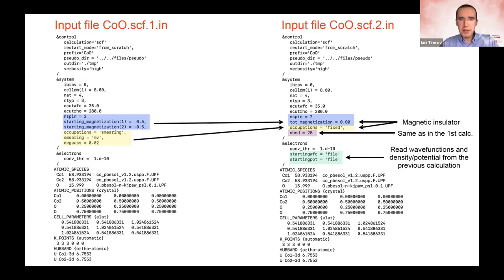In the first calculation, which was the DFT calculation, that was the metallic ground state. You remember we computed in exercise 1 the projected density of states, and we saw that it is metallic. But now we apply plus U, and we remember from exercise 1 that when we apply plus U, it opens a gap. So we went from the magnetic metal to magnetic insulator. But before going to the next HP calculation, we need to perform an additional SCF calculation.